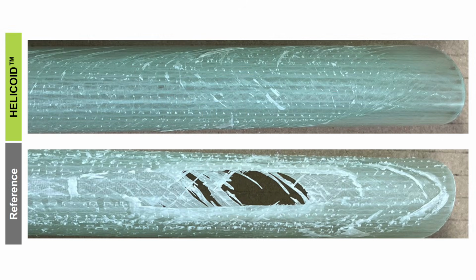So we have done extensive rain erosion testing, comparing a conventional substrate, as you mentioned, a plus minus 45, 0 degree fiber orientation substrate, and we use the exact same fiber, the exact same resin, the exact same manufacturing process, but with our helicoid design leading edge, to show that instead of getting large chips of material being removed very quickly as the erosion progresses, in our case, we have a very smooth and slow erosion of the substrate. So for once, you reduce by more than 70% the eroded mass under the same testing conditions.